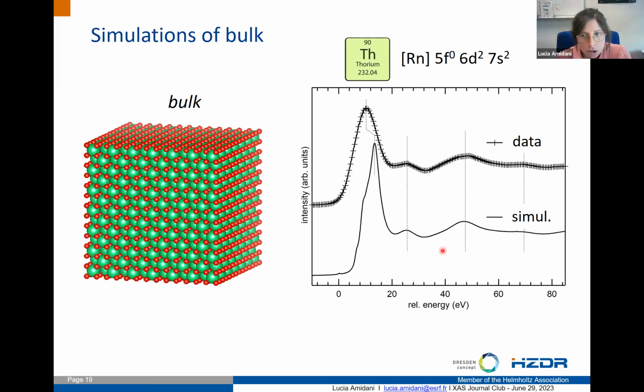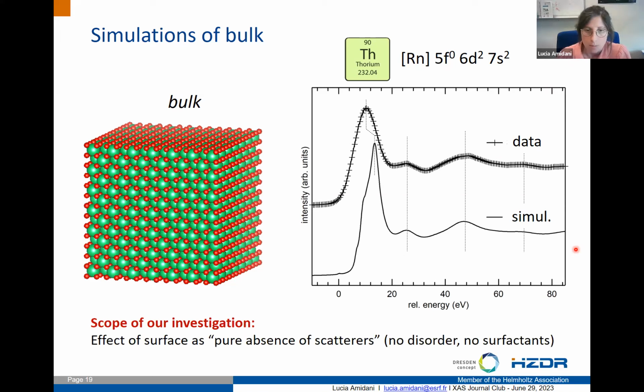So the simulation of the bulk is pretty good. Very important is that we reproduce the post-edge structure that we're interested in. The white line is not at the correct position, but the shape is still good. But in these specific studies, I'm not focusing on the white line, because the scope of this investigation was to understand the effect of the surface intended as a pure absence of scatterers. So I will not consider disorder at the surface or surfactants.